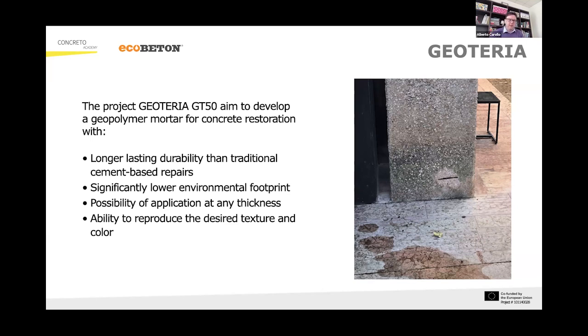It is better to think of geopolymer more like a plastic, if you want, than a cement. And so there is no shrinkage, and this allows you to apply from 1 millimeter to 20 centimeters in one go, because shrinkage is another big issue for concrete repair, and of course the ability to reproduce the texture and color that you want. We are in the field of restoration, and these objects are very good. We don't want to patch them in an Arlecchino way, okay?